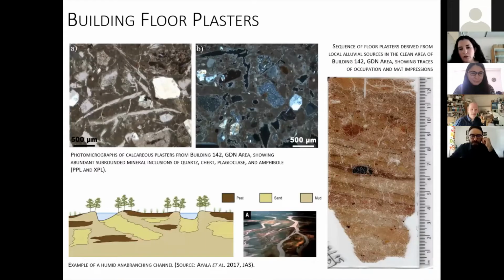One interesting conclusion that we reached through this analysis, and that allowed us to link environmental change with on-site evidence of subsistence at Çatalhöyük, was the characterization of late Neolithic clusters at the site. Significantly, calcareous floors derived from marl sources are substantially coarser in the late built environments excavated at Çatalhöyük than in those observed in earlier buildings at this site.